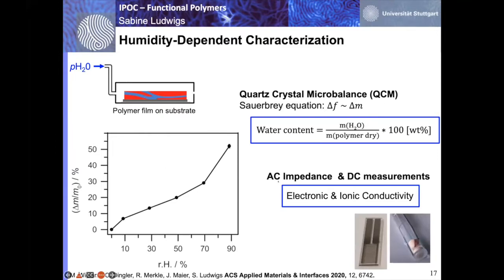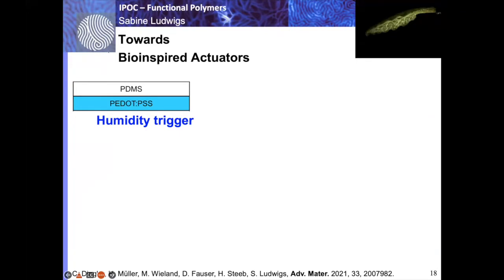We have also used AC impedance and DC measurements to decouple electronic and ionic conductivity. The ionic conductivity becomes prominent especially at high relative humidities, because then the ions can nicely get transported through the blue phases in such a co-continuous morphology. Coming from that, we wanted to build actuators, since we know that the PEDOT:PSS can take up the water, so it swells in water.